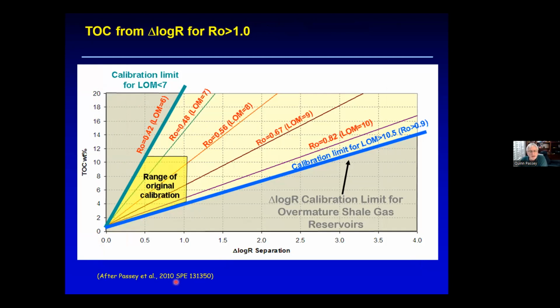In our 2010 paper, we had taken our data at low maturities and extrapolated it based on one well, but we find that if you actually plug in the equivalent LOM or vitrinite reflectance equivalency here, you would underpredict the TOC in shale gas wells. Until we got into unconventionals, we didn't have much data in the higher maturity, over mature, if you will, gas wells.